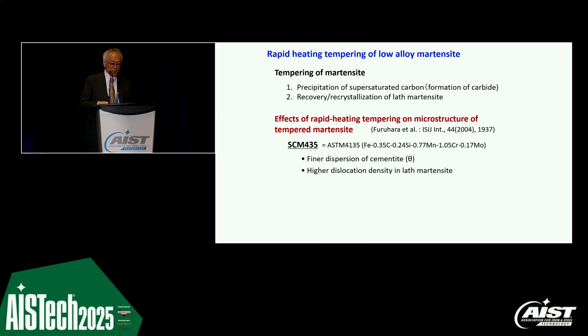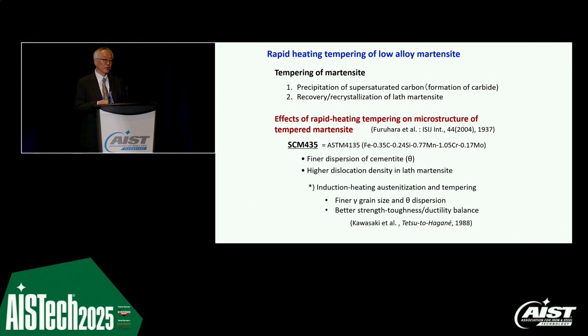Also, rapid heating can be important for tempering of martensite. Tempering of martensite is, of course, known for the precipitation of cementite as a precipitate, and also the recovery of the high dislocation density in martensite takes place. But when we apply rapid heating tempering, we can get a finer dispersion of cementite and also retain a little bit higher dislocation density. As a result, we can get higher strength and also better toughness by applying this kind of heat treatment.